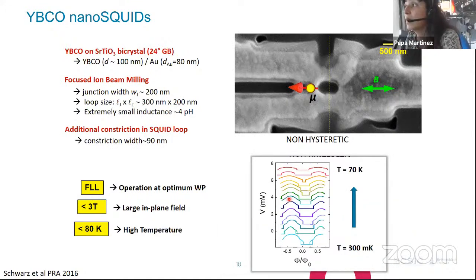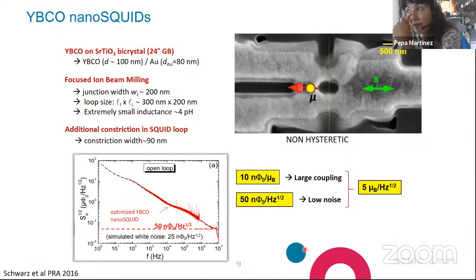Of course, they are also able of working up to large temperatures of 70-80 degrees and also down to very low temperatures, okay? Finally, thanks to the small size of this nanoloop that yields extremely small inductances of just a few picohenry, we also obtain extremely low values of the flux noise at large frequencies, okay?